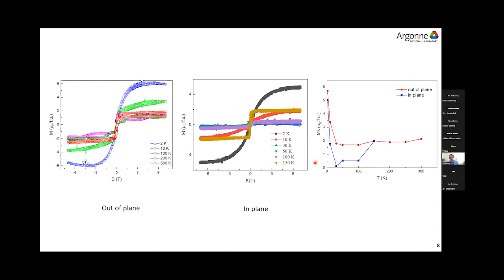And we also checked the possible anisotropy of the magnetic moments, in order to check if the manganese moment could possibly fall into the hexagonal plane. So we measured the in-plane magnetization of the film. Actually, the saturated magnetization indicates the moments are mostly along the c-axis at low temperature. But there's a sudden jump below 10 Kelvin. This we think comes from the terbium moments, which we can discuss later.